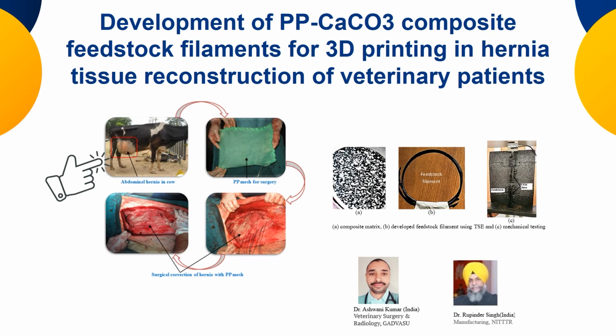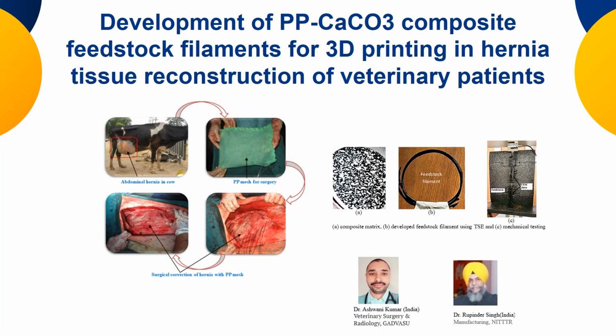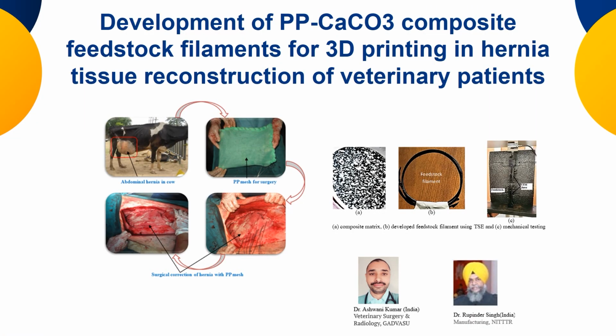Now what I have to do is cut this tissue, right? After the surgery we put a polypropylene mesh over here. Normally, the life of these types of animals is around 8 to 12 years, and the life of the mesh that we use is normally more than 30 years. So there is no problem in using these types of meshes. What we have actually done is, for a fast recovery of the patient and better wound healing, from the literature, we prepared a polypropylene with a reinforcement of CaCO3 in the form of a composite. So you can see that the composite has been prepared.